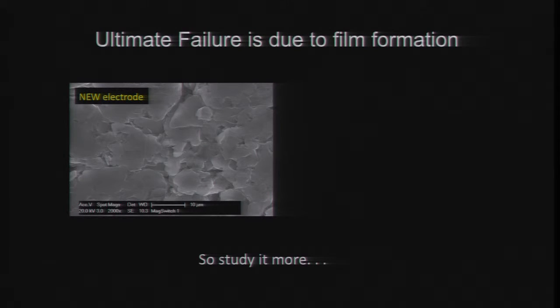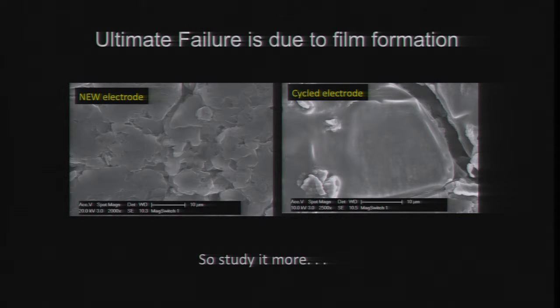And so one of the things that we're looking at here at CMU is understanding why this failure is happening. One of the most common things we all think about in the battery research community is the formation of a film on the anode side called a solid electrolyte interphase, an SEI layer. This is a pristine harvested electrode from one of those batteries. It's a graphite system, and you can see these nice graphite flakes. It's very clean. And this is after 600 or 700 cycles at elevated temperature. You've seen it's all got coated up with this gunk.